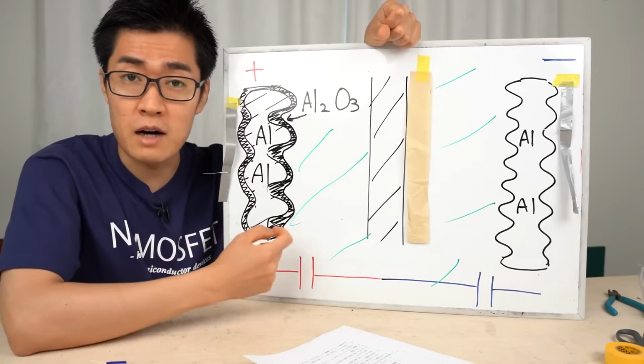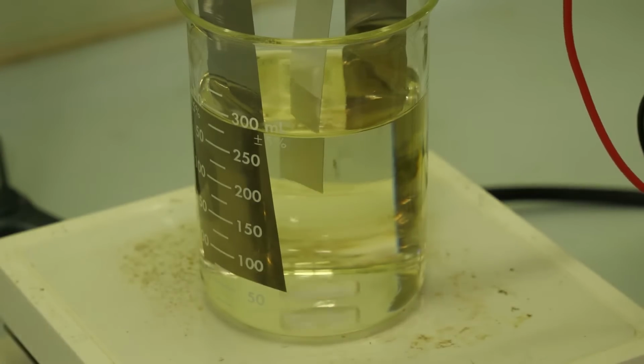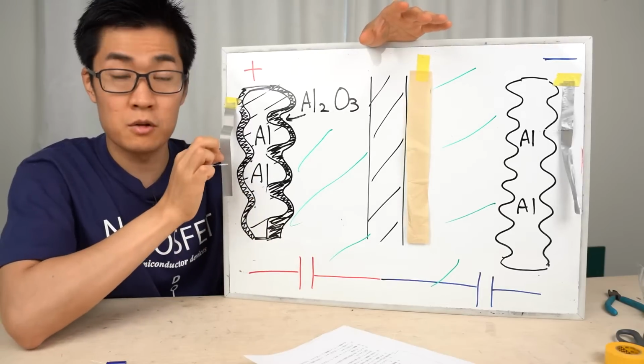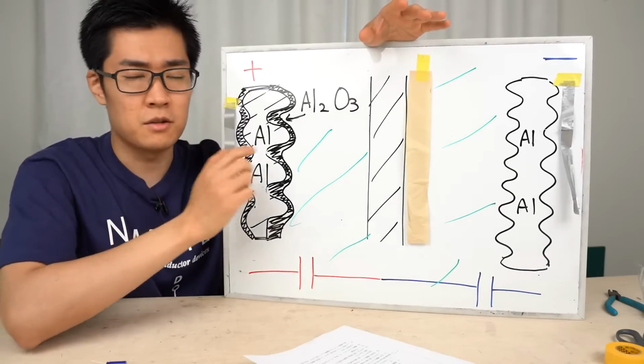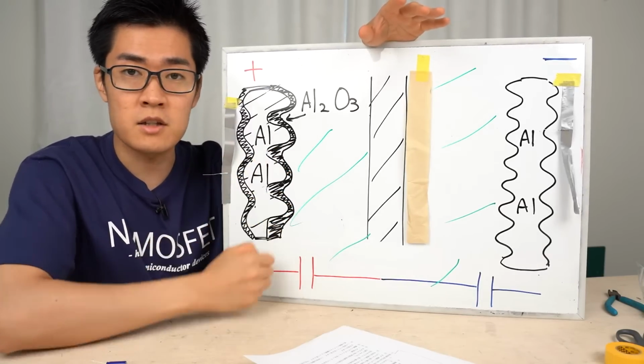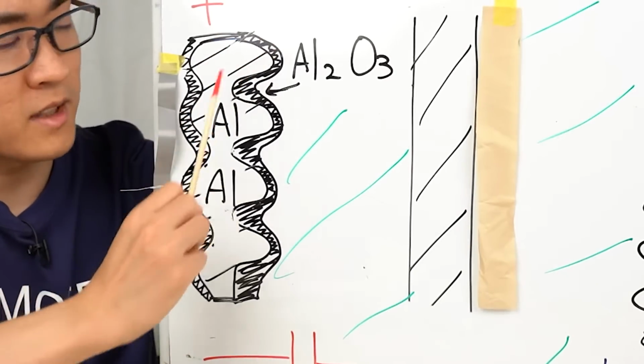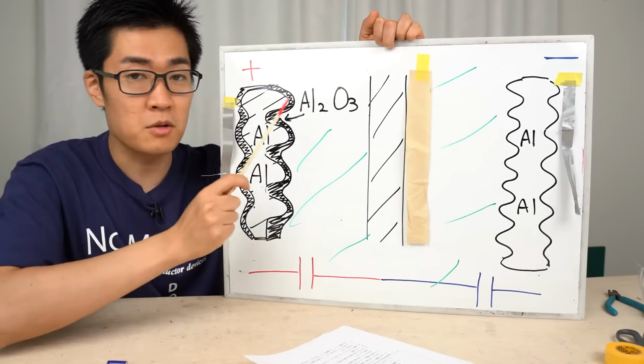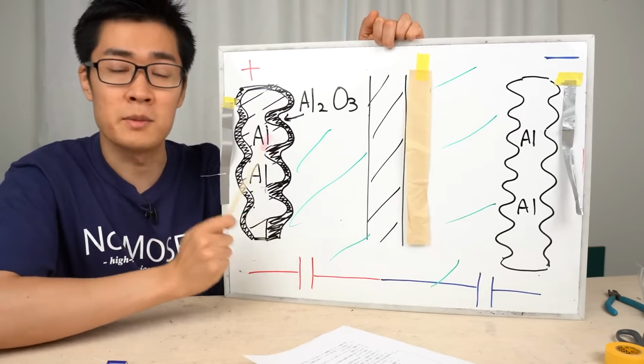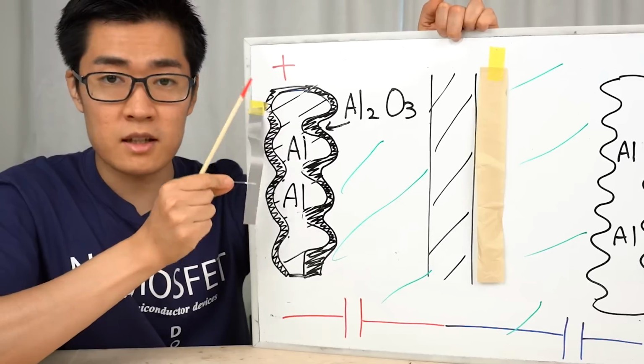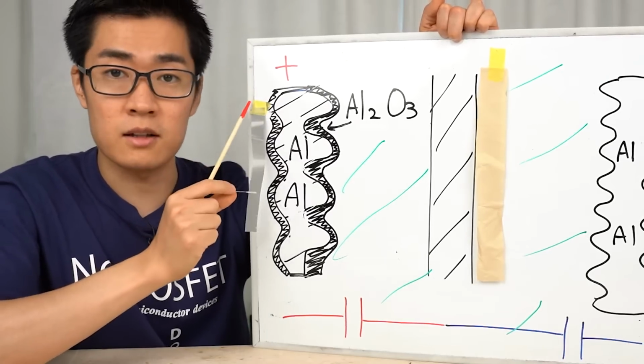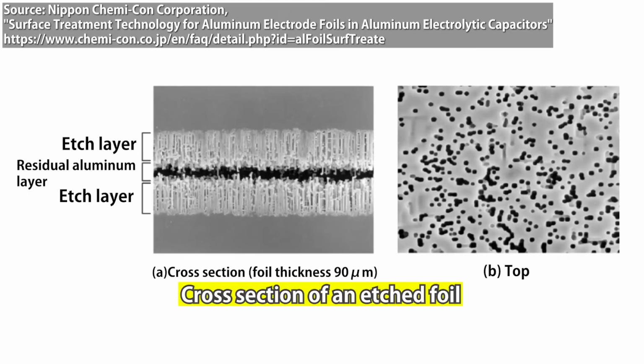Chemical treatments are applied to the foils: etching and forming. Firstly, in order to increase the surface area of the foils, both the anode and cathode foils are etched. Etching increases the surface area. It's a process to melt the surface of the aluminum foil, creating fine holes or pits. You can't see how the surface area increased with the naked eye, but using an electron microscope, you can see